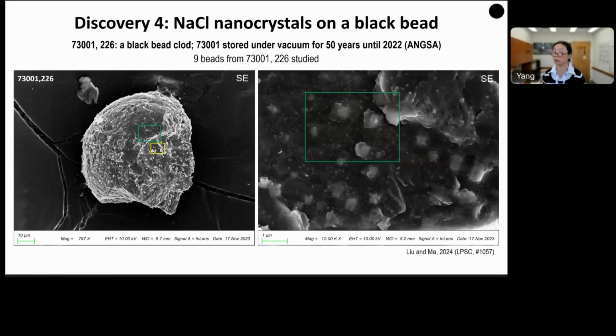Okay, discovery 4. This is the sodium chloride discovery that was in the original talk. We looked at the 9 beads from this sample, and here is the only bead on which we observed the sodium chloride. Here is the overall image, and we are looking at 2 different areas. In the abstract, we said we only found it in this kind of depression area. And now with further observations, we actually see the sodium chloride widespread on this bead rather than just confined to one area. Here we look at the green area over here.